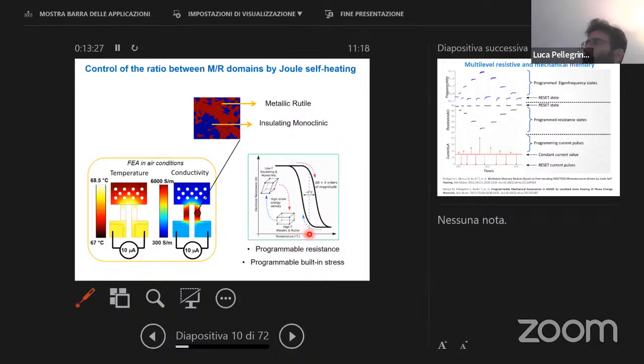We can do even more. We can stay in this temperature window by thermalizing the sample, and we can apply a quite relevant current to heat up the system. The heating is concentrated in this region, so we can also change the conductivity, because in this region we have a mixed state between metallic rutile structures and insulating monoclinic structures. Later on, you can see that we can play with the current to change the ratio between these structures.